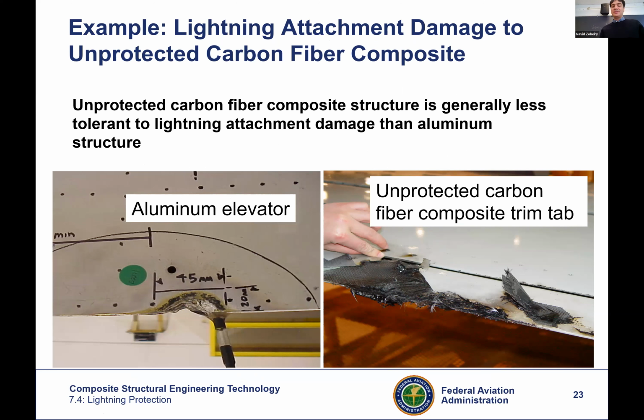And you probably don't see, so there's resin burn off, resin goes through pyrolysis. There is probably delamination. You're going to probably break the fibers. But the extent of damage is probably a lot more extensive than you can see in this corner. But this corner is probably completely gone because of the temperature that is experienced.